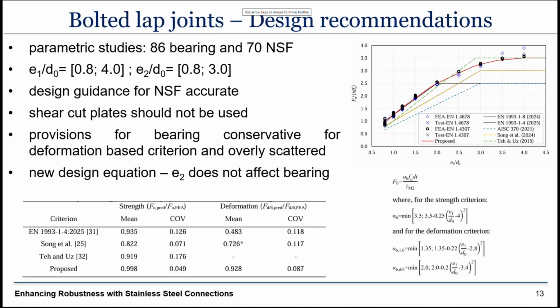The modeling for high strain rates is still ongoing, so we haven't completed that. That's why I'm presenting only the results for static loading conditions. We varied the end distance as a function of the bolt hole diameter from 0.8, which is below what Eurocode allows, which is 1.2 as the minimum allowed, but we were doing research, so we wanted to see what's the effect of that.